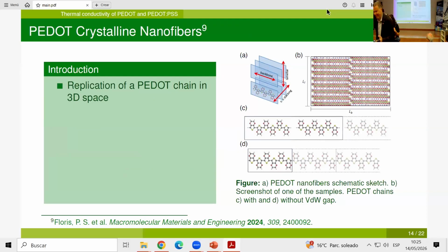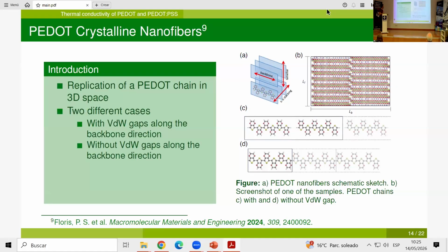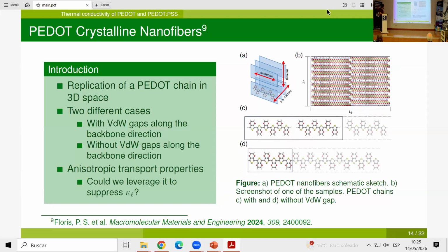We also studied another kind of system. The systems we were considering until now were amorphous PEDOT and PEDOT:PSS. In this case, we also studied crystalline nanofibers of PEDOT, which we created by replicating PEDOT chains in 3D space. You can see an example here. There are two different cases: a case with van der Waals gaps along the backbone direction, like we see here in figure C, and one without van der Waals gaps along the backbone direction. We wanted to know if we could leverage anisotropic transport properties to suppress lattice thermal conductivity.